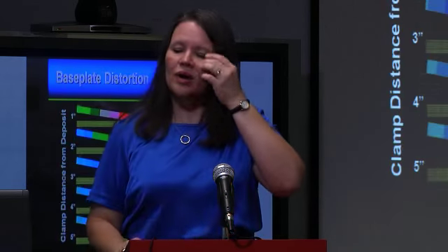And we've seen this crack 1-inch titanium plate. So these are not insignificant. They're scary stresses if you get it too hot. Something that really needs to be controlled in order to put it into practice. Again, this is another set.